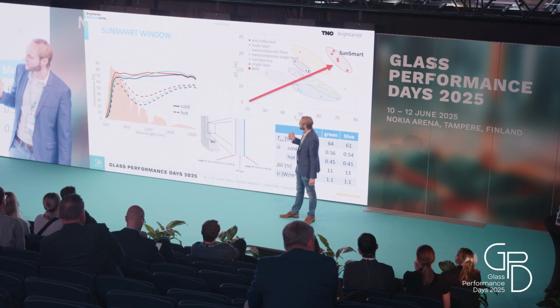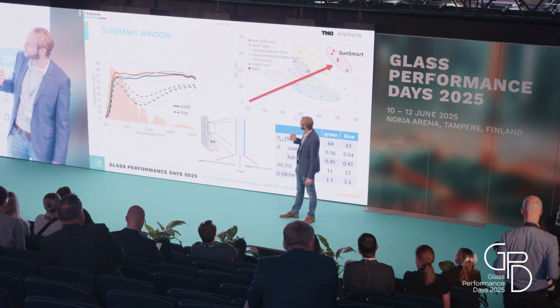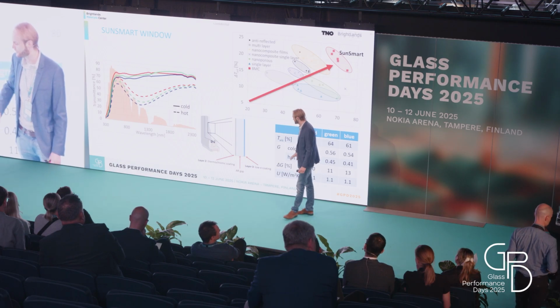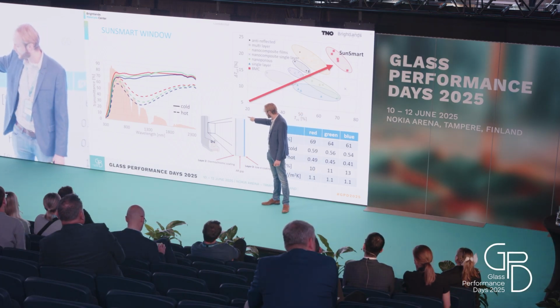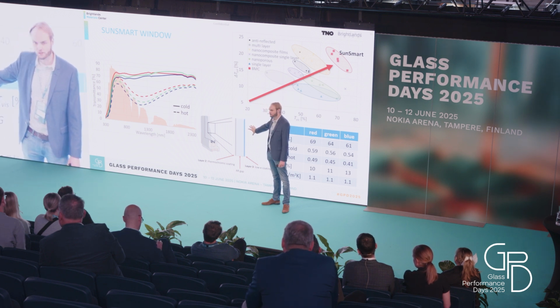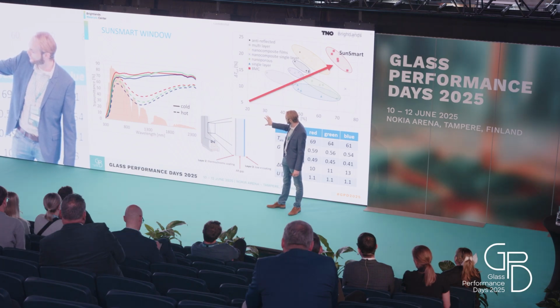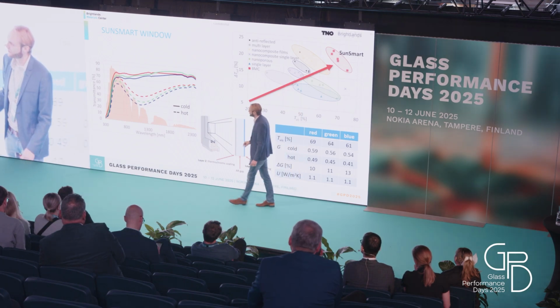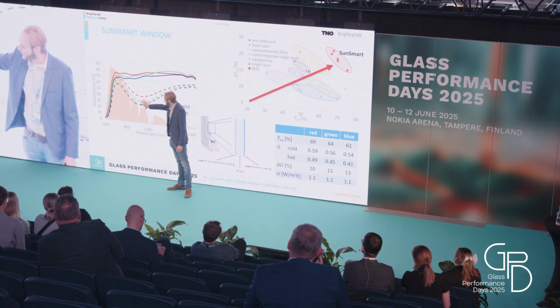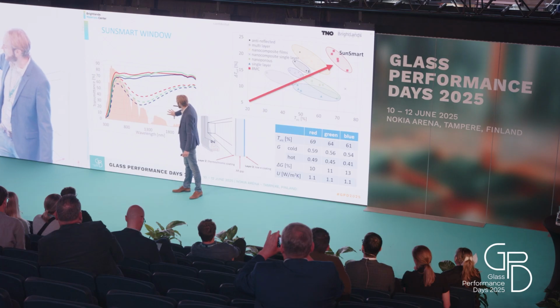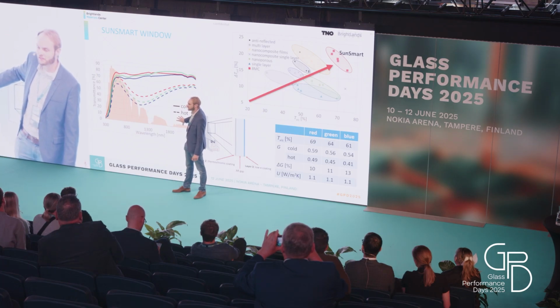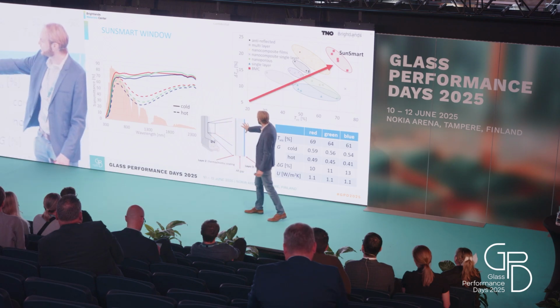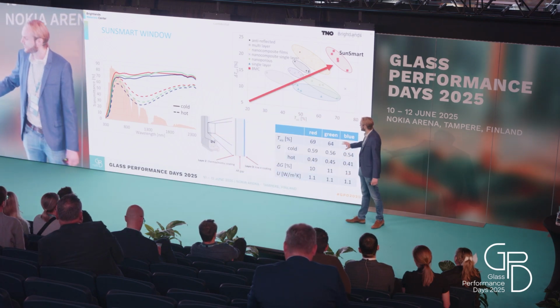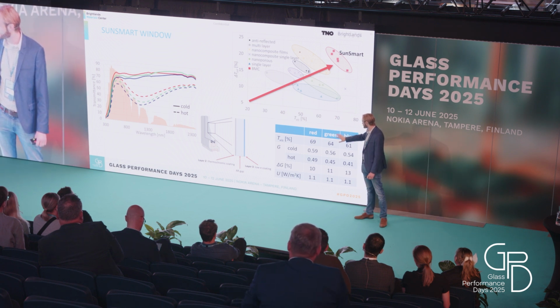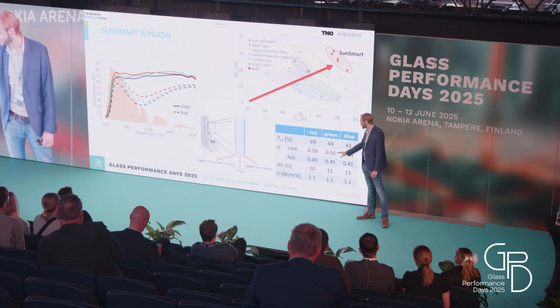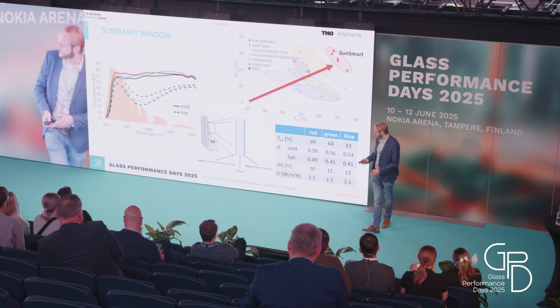The technology is solely focused on the interaction with sunlight, which means, in an IGU, you still need to have your insulating properties. And these insulating properties in the smart window, we get by combining the thermochromic coating with a low-E coating. So it's not only one coating, but a combination with the current low-E coatings. And that's the second reason why we are focusing on the range between 800 to 1400 nanometers, because you know that low-E coatings largely cut off all the longer wavelength infrared light. So that is anyway not available for modulation. But with this smart combination, we can make smart windows which have a high transparency between 60 and 70%, and you can modulate the G value between 10 and 13% between the cold and hot state, depending on what kind of coating you're using.